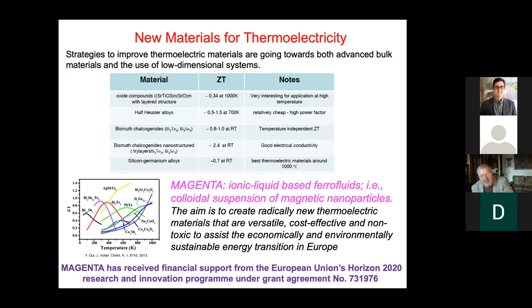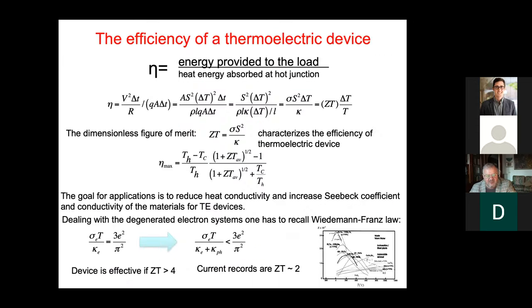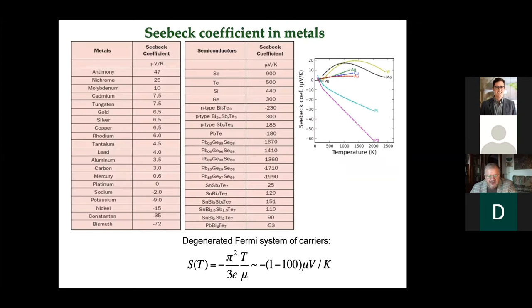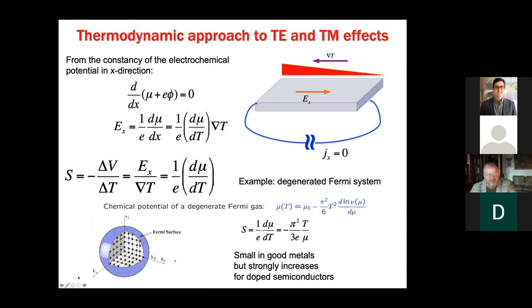indeed reachable. Now, two words about Magenta. So, ionic liquid-based ferrofluids are colloidal suspensions of magnetic nanoparticles. To understand why we face electrolytes, it is enough to take a look again at the Kelvin formula. S is proportional to dμ over dT. When we deal with a degenerate Fermi system, this value is small. But in electrolytes, you deal with a Boltzmann system, and the formula for chemical potential is just minus T log concentration.